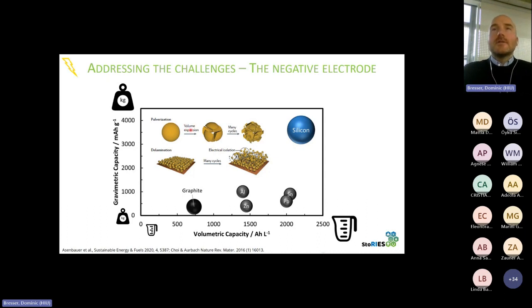So you've seen on the previous slide already that this alloying reaction comes along with a big volume expansion. Upon lithiation, it's an expansion, right? But upon delithiation, it's shrinking again. So we have very extensive volume changes, which means a lot of stress on the particle. So frequently, if the particles are too big, we're facing pulverization issues that are depicted here. And the stress is not only at the particle level, but also at the electrode level, then potentially resulting in delamination issues and electronically isolated particles that are not available anymore for any further lithiation and delithiation reaction.